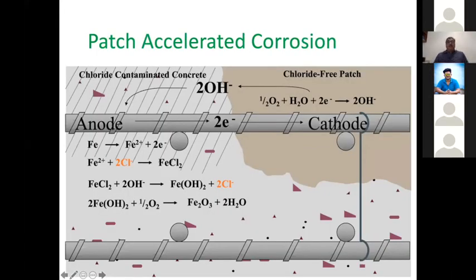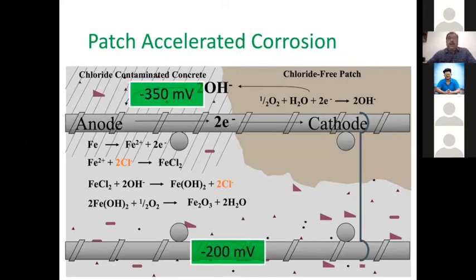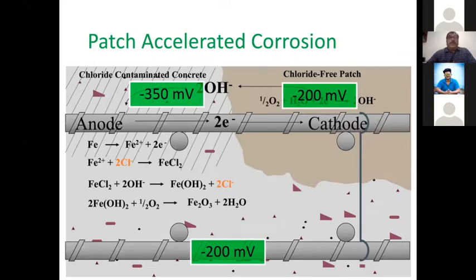Again, if I go to the same corrosion cell that I showed you earlier, and what we are doing for the patch repair: we have a proper saw cut, we chip out, we clean the rebar, we go beyond the rebar, apply various protective coatings on the rebar, and use a chloride-free patch. By doing this, we have introduced a new condition wherein the new patch and the non-contaminated area will have a similar half-cell potential of corrosion, but the concrete which was not cracked and has contamination adjoining, which we didn't remove because the concrete was good, will have a more negative half-cell potential. Because of this difference of potential, what we call delta.